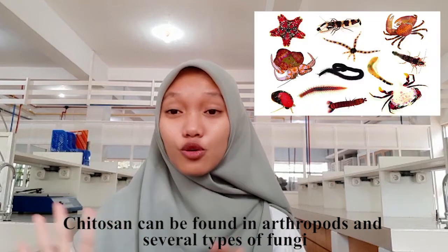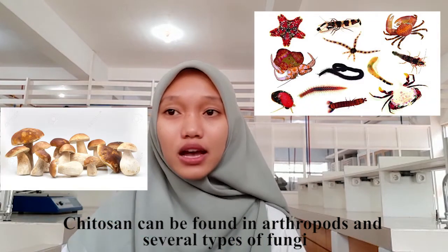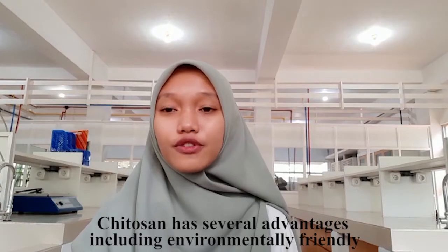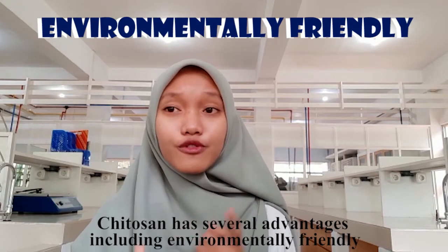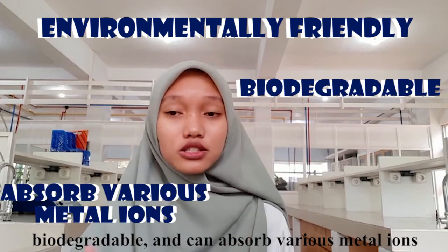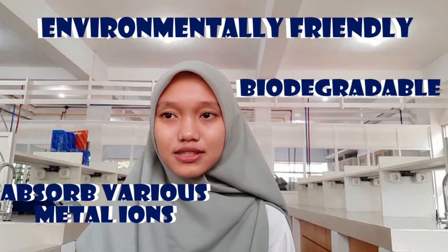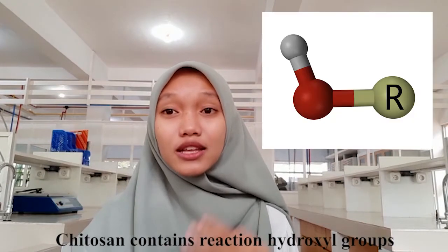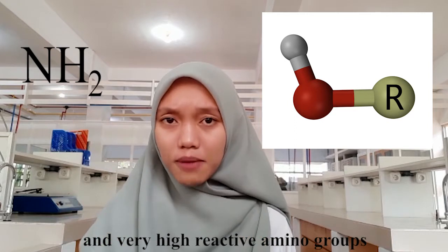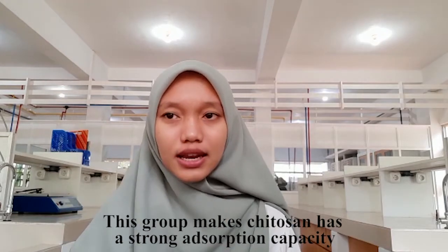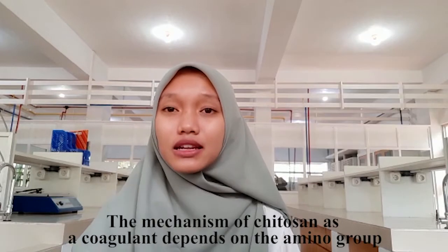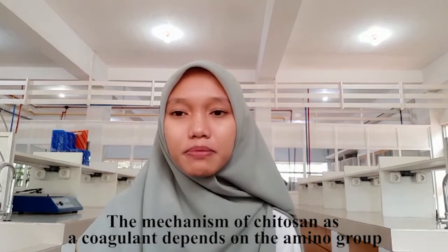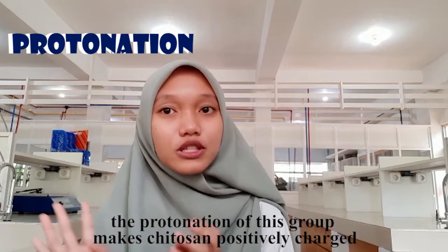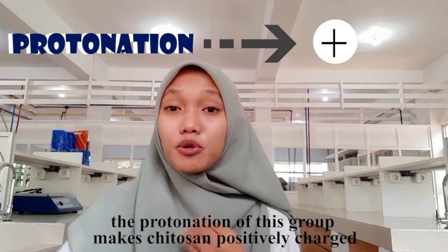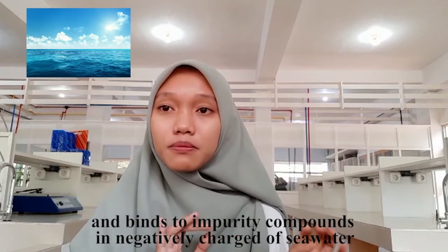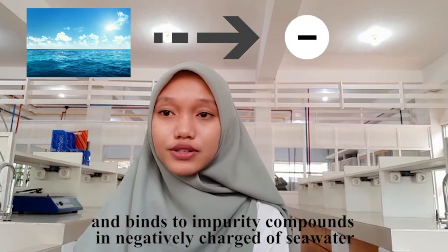Chitosan can be found in arthropods and several types of fungi. Chitosan has several advantages, including being environmentally friendly, biodegradable, and able to absorb various metal ions. Chitosan contains reactive hydroxyl groups and highly reactive amino groups. These groups give chitosan a strong absorption capacity. The mechanism of chitosan as a coagulant depends on the amino group. The protonation of this group makes chitosan positively charged and binds the impurity compounds in the negatively charged seawater.